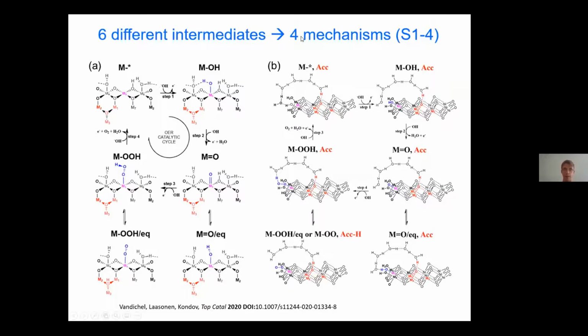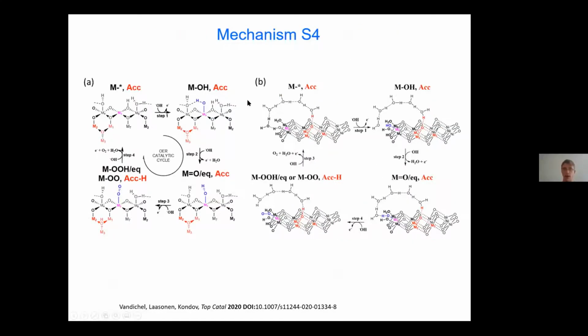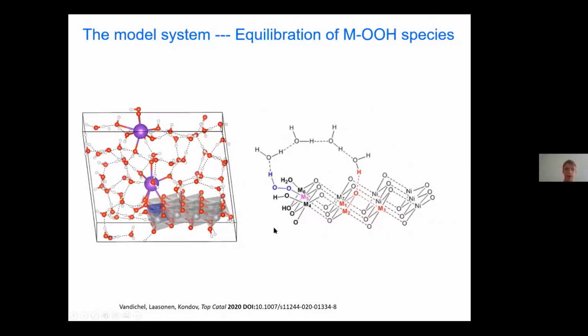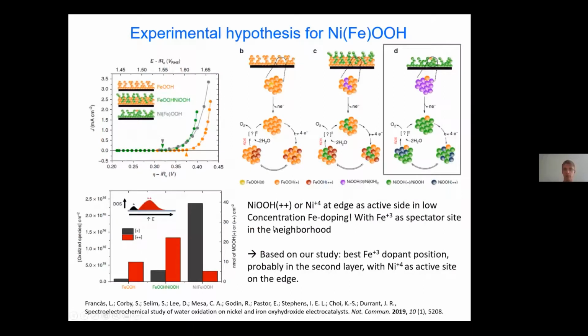So then we can actually come up with four different mechanisms. The mechanism that was most interesting was S4. So S4 goes via an equilibrated oxo and an equilibrated OOH. So that's a metal OO state with a hydrogenated acceptor site. So let's go to the results.